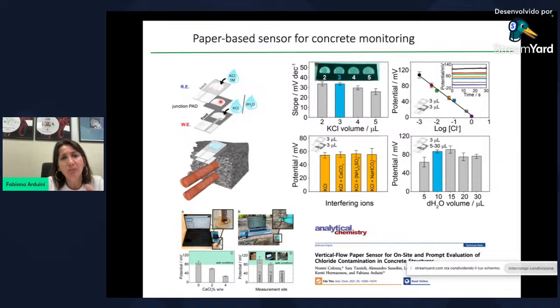We add a junction pad and we add distilled water to dissolve the chloride on the concrete, or KCl in the case of the calibration curve. So in this case, by adding only 1 drop of 1 molar KCl in the first reference pad, and distilled water with the pad in contact with the concrete, we are able to evaluate the corrosion of the structure. Again, we demonstrated this and published it in the Analytical Chemistry journal.